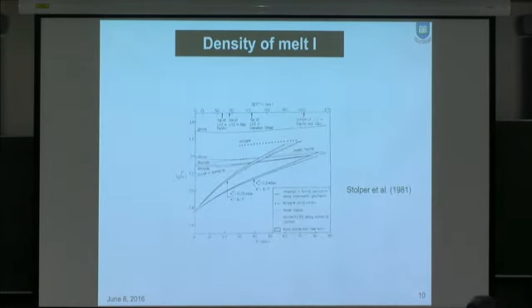This was first pointed out by Stolper, in a 1981 paper. Basalt melt starts from here compared to olivine density. Olivine is denser than basalt, that's why basaltic melt goes up. But if he calculated the depth variation of density of olivine and melt, olivine density doesn't change so much because olivine is so stiff. But melt is so soft, density goes up in a crazy way. Okay, so this is one very important reason why melt density could become very high.